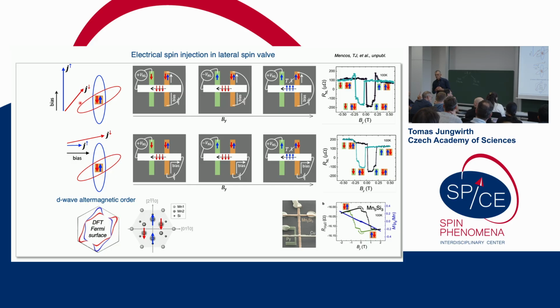Go ahead. So where is the By with respect to the axes that you are showing? Because I expected that all arrows should be along... So By is, sorry, the arrow means that I'm increasing the magnetic field, but the y axis is the vertical axis along the magnetization. Which is out of plane? No, which is in plane, along the electrode, because the electrode has a shape anisotropy, and that defines the magnetization which is along the electrode.